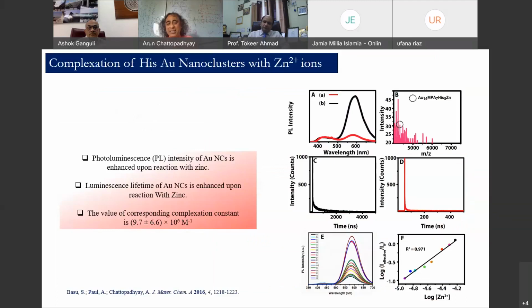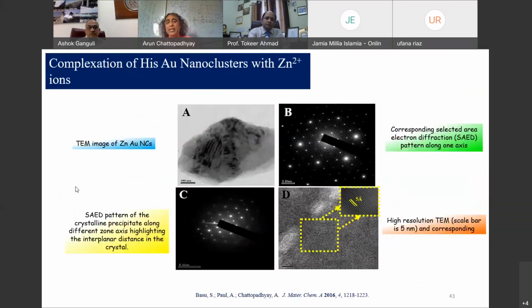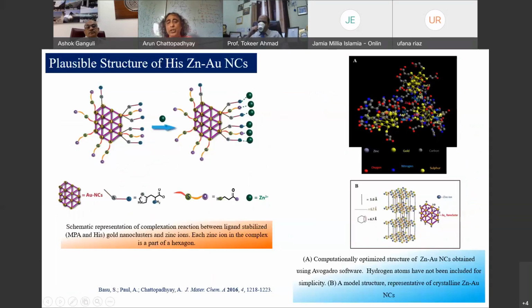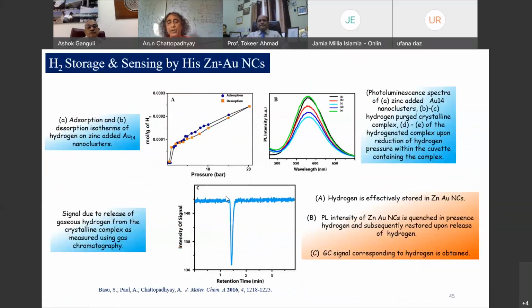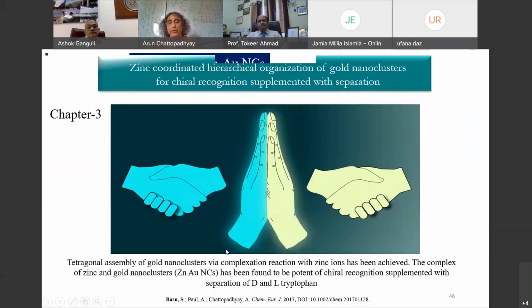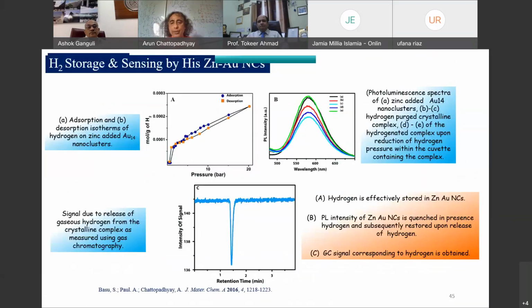So, I will go quickly, we had single crystalline materials. Through TEM, we could find out most of the parameters. Sometimes we also got XRD, but very rarely. This took a long time to establish the structure. Three months for one structure it took. But this was the idea that you can store and recover hydrogen. That is idea one. That cannot be done using clusters. That can be done using assembly of clusters.